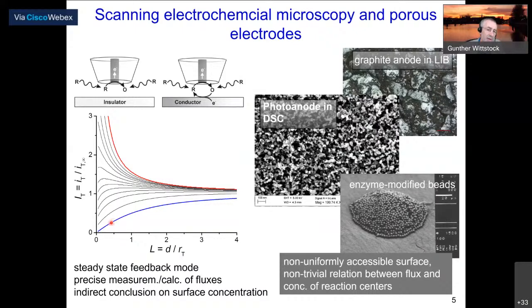In between these two extreme cases, where we have no reaction at the sample or a diffusion-controlled reaction at the sample and at the tip, we have all sorts of cases in between where we have a finite rate constant, where the mediator is regenerated, but not with infinitely high rate. And then we get curves like this, and then we can make, in principle, two experiments. Either we keep the distance constant and scan our microelectrode laterally over the surface, and then we observe the changes between the different curves at the constant distance, or we pick one curve and approach the surface and make a kinetic analysis where, by comparing our measured data to simulated data, we can extract a rate constant.